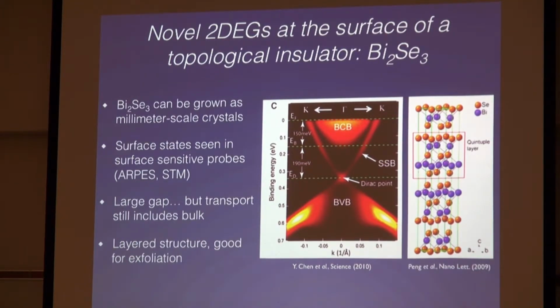And if you look at these materials in something that's very surface sensitive, you see this very nice picture where you can see, in addition to the bulk conduction band and valence band, there's this surface state that has a linear dispersion. Further, they've shown that along this arm, if you look at this particular arm, it's been polarized. On this other arm, if you look at the other side of K, minus K, it's been polarized in the opposite direction. So very nice ARPES and STM work. Anything that's surface sensitive, topological insulators look very good in. In transport, not so much.